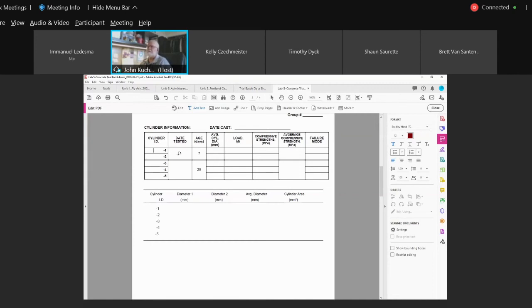The date tested, well, if you made it today on the 9th, okay, you would have been testing the 7-day on the 16th. And if you made it on the 9th, you'd be testing 7, 14, 21, 28 would be April 9th, give or take. So in other words, 28 days later than date cast. The average cylinder diameter, okay, you're going to have diameter 1, 90 degrees to it, you're going to have diameter 2, your average diameter, the cylinder area.